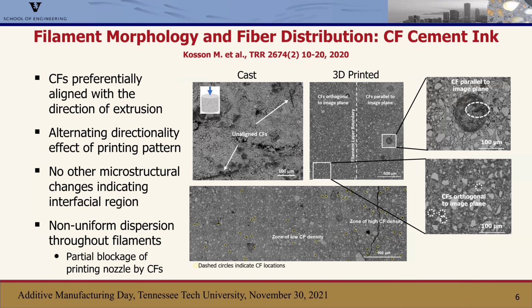So when we were printing with the carbon microfibers, as I mentioned a second ago, we saw that they preferentially aligned in the direction of extrusion, which when we printed in a rectilinear pattern where every layer was offset 90 degrees from the previous layer, produced an effect where you had an alternating directionality of the printing pattern. So in this picture here on the right, you can see that in the left half of this cutout, there are fibers that you can see pretty much everywhere, and they're difficult to see, but you can see they're circled in the cutout on the right.